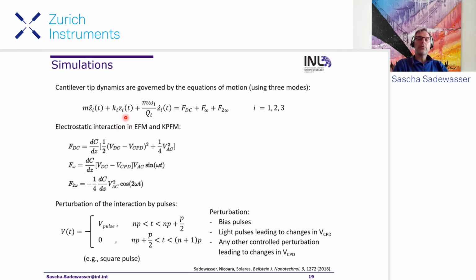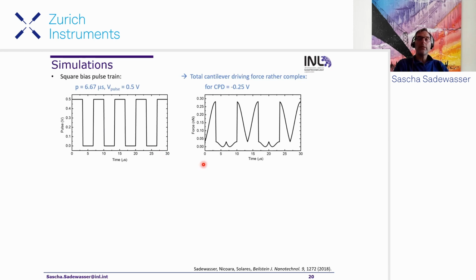And here we now introduced looking at this cantilever motion for Kelvin probe. So we again look at these three forces from applying an AC voltage, nicely introduced by Stefan earlier this morning. And then additionally, we put in a voltage perturbation: voltage pulses, square pulses with a period P and a duty cycle of 1/2, that can reflect bias pulses directly, but could also reflect the CPD change induced by light pulses or any other perturbation that has an impact on the CPD of our sample. So here is again this pulse train that we send, and we only look at the electrostatic driving force, so we ignore the cantilever oscillation that is excited by the piezo. And this electrostatic driving force then looks actually quite complicated.